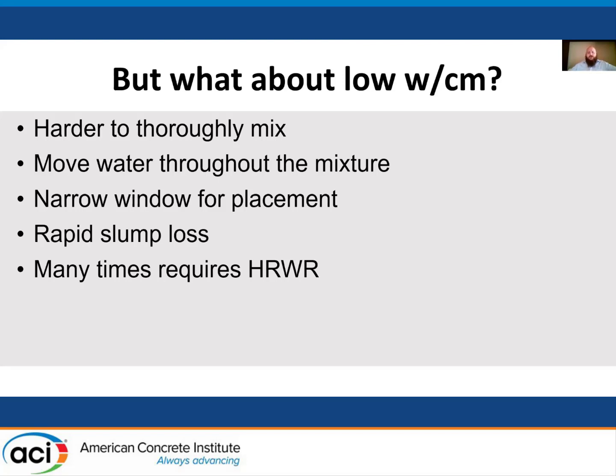So when we talk about lower amounts of water, lower water cement ratio, you're also having a more narrow window of placement. From whenever you're done mixing and it's all mixed together, to whenever you place it in the molds and the forms, you're going to have a much smaller window, because there's just a lot less water. So you're going to have a lot more rapid slump loss too. It's kind of crazy how quickly you can lose your slump, in just a very short amount of time. And so you got to be really conscientious whenever you're placing mixes like this.